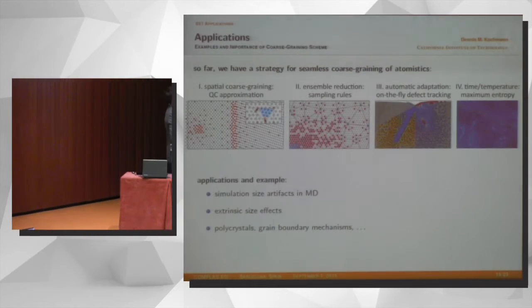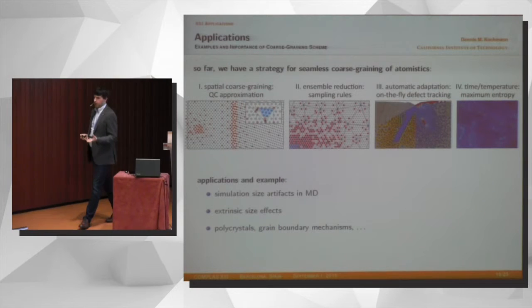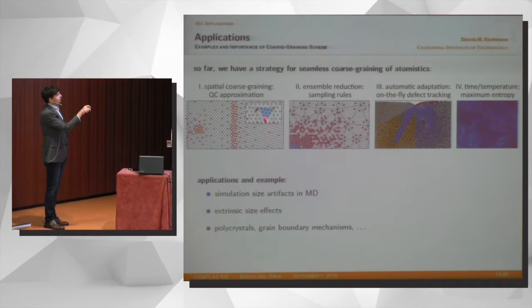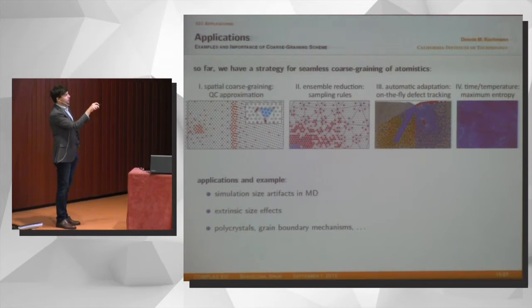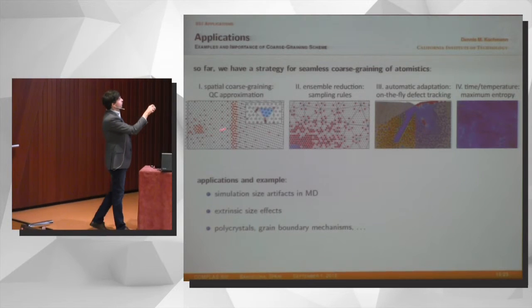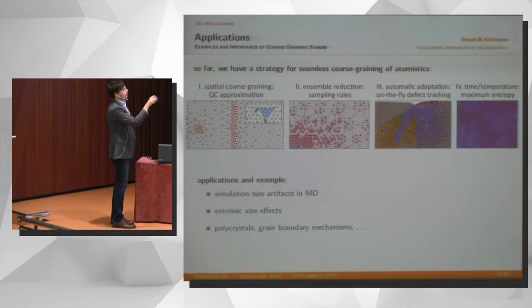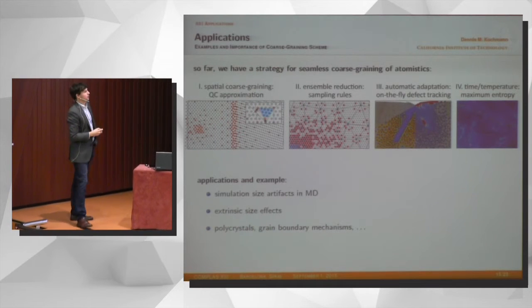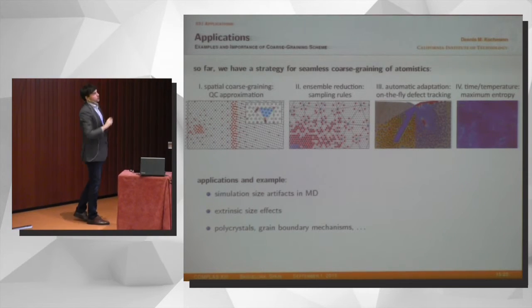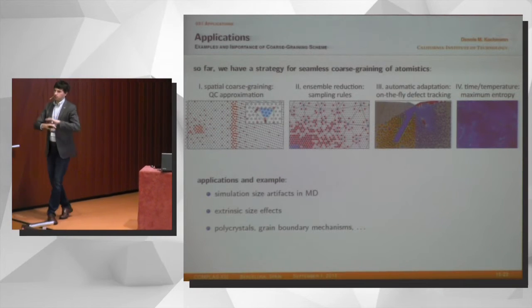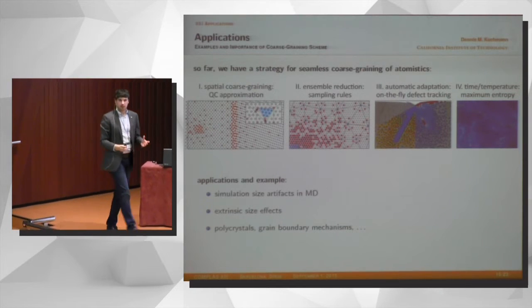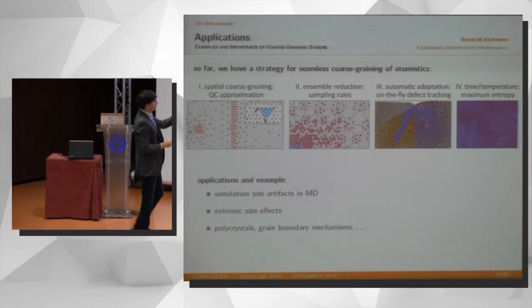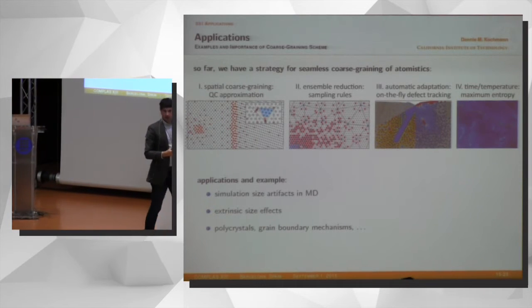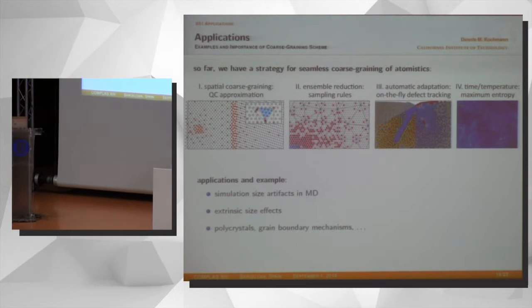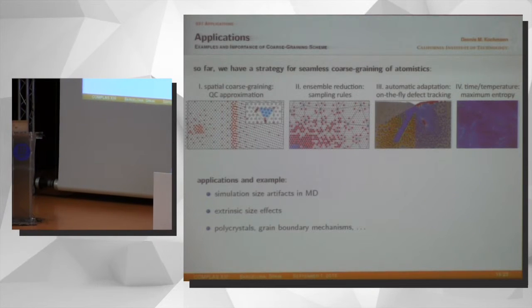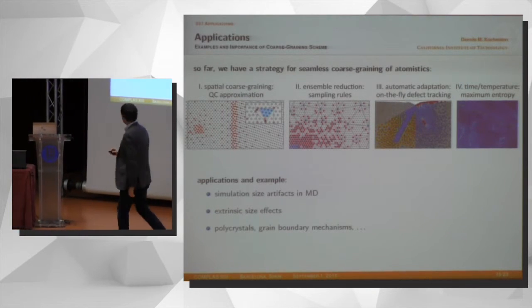And so all of these four steps, one, two, three, four, is what we use in order to go to bigger scales. First, we get rid of many degrees of freedom, so we only keep a few degrees of freedom where we need them. Second, we don't compute the energy of every atom, but we pick our favorites. I presented this new sampling scheme that works well. On top of this, we use automatic adaptation. So nobody has to know where atomistics is needed. The code will find out itself as it runs the simulation. And finally, we can also do this at finite temperature, and we can run dynamic simulations at bigger scales than what's normally feasible by atomistics.